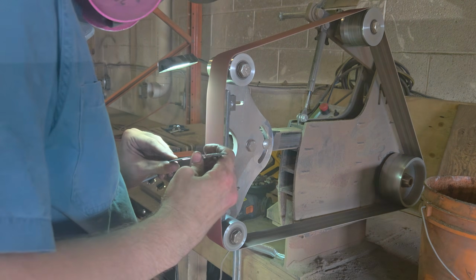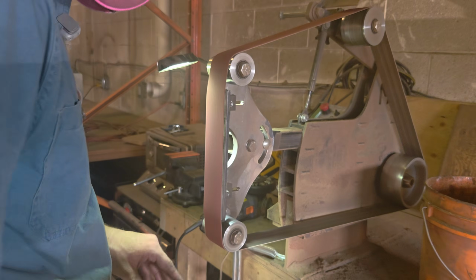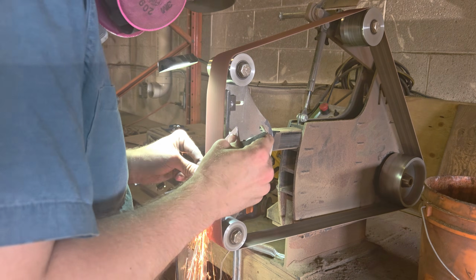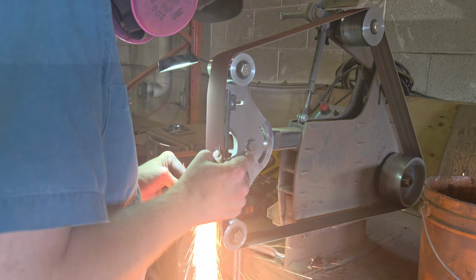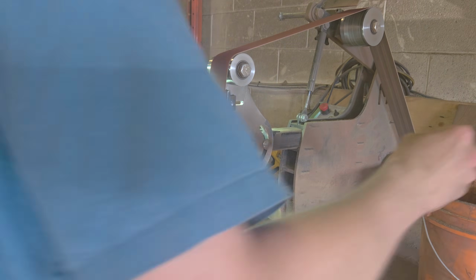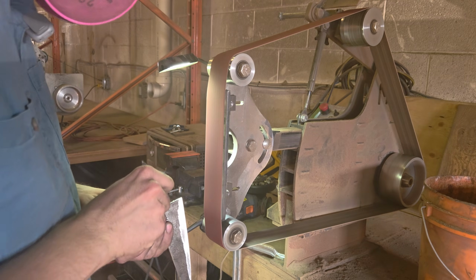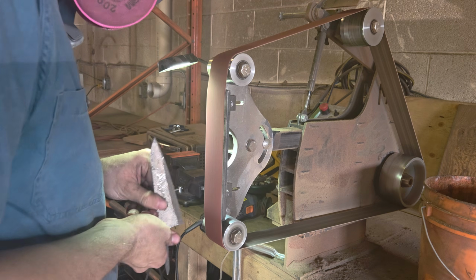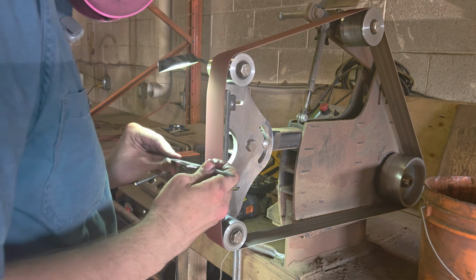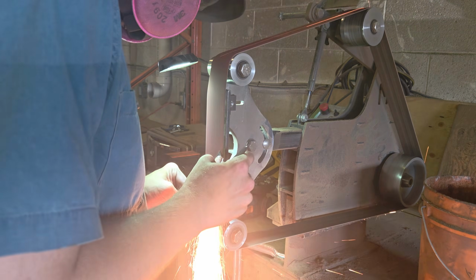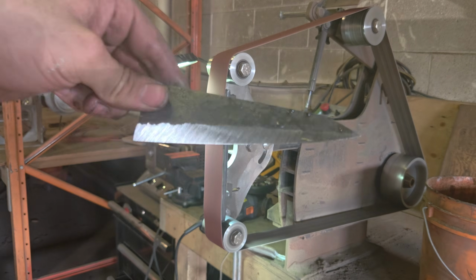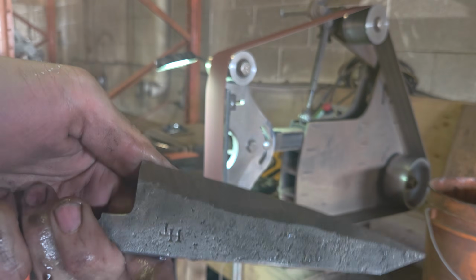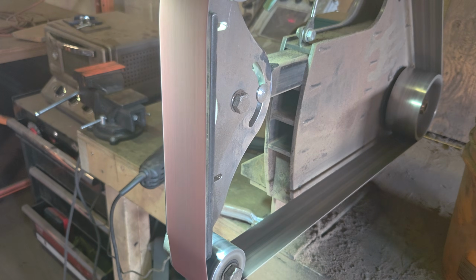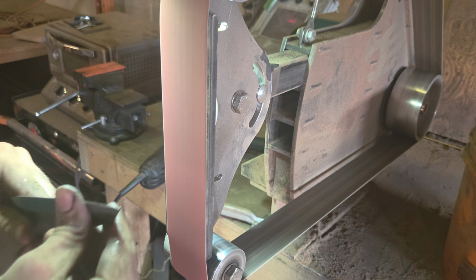Another thing that really helps is using fresh belts. It sucks to always have to buy belts, but fresh belts really cut material way more efficiently, save a lot of time, and you ruin fewer blades because it keeps the temperature down. I like to use VSM 60 grit belts for most of my bevel grinding. Once I pretty much go all the way down really, really thin on the 60 grit, and then go to my polishing belts.